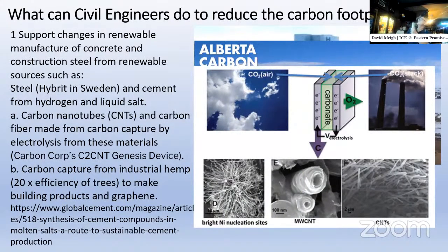They show how they combine CO2 and air in this electrolysis system with a carbonate in the center. And it produces oxygen and carbon. So it strips the oxygen out of the carbon dioxide and produces these nanotubes as fibers or as rolls of fiber or strands that can be woven together into a dark material that we can use for reinforcement.